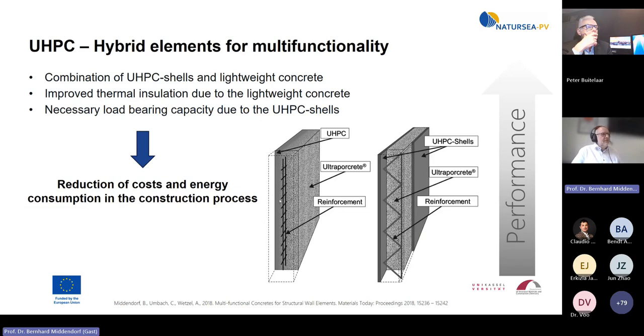So you see it here. We have hybrid elements for multifunctionality. That means we combine the UHPC, you see it here on the right. We combine UHPC shells, traditional, and put in a very dense, not a very light UHPC, but with a high compressive strength in the area about 100.